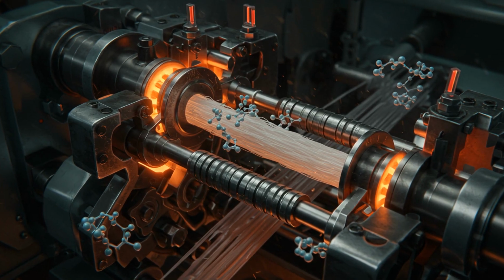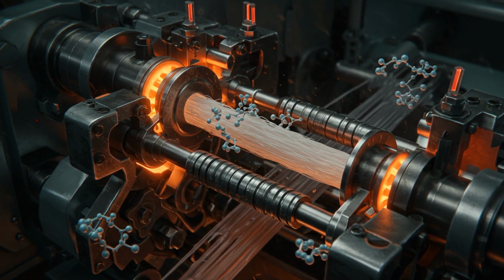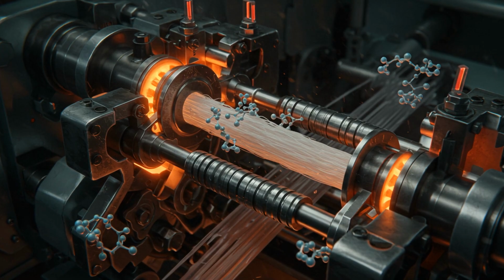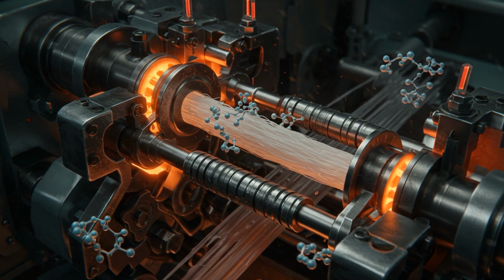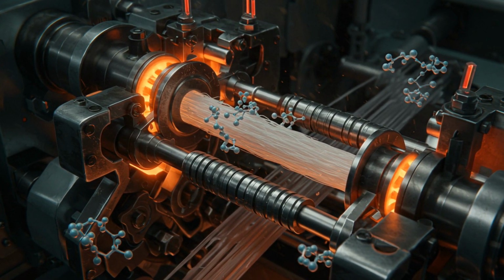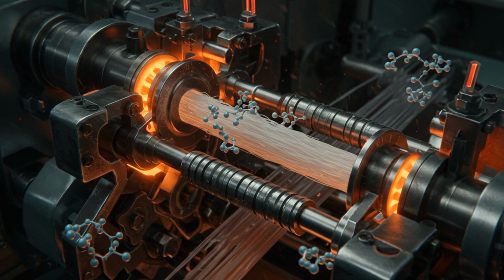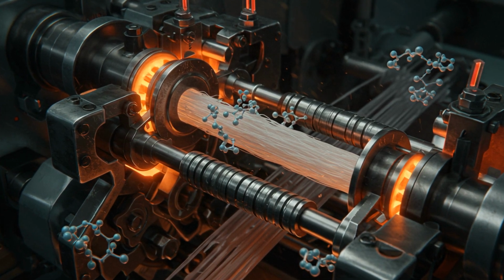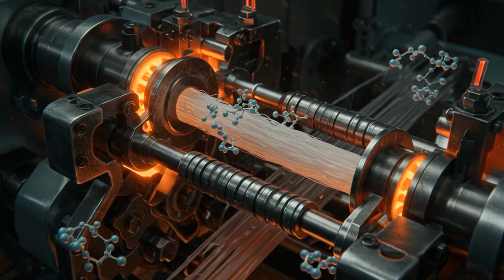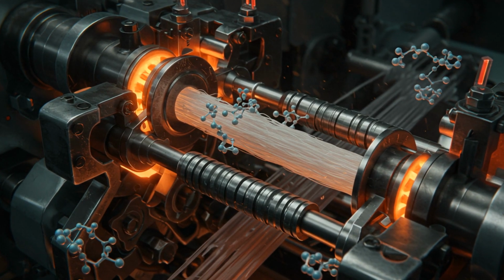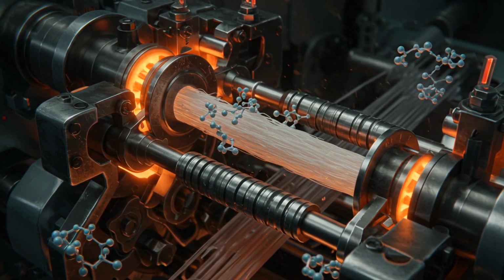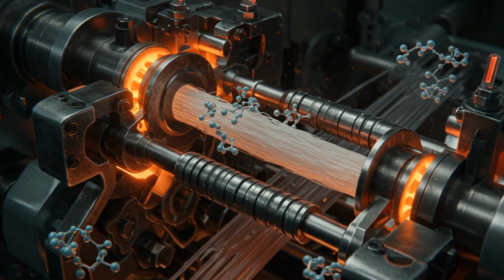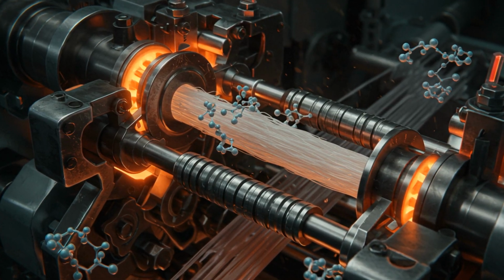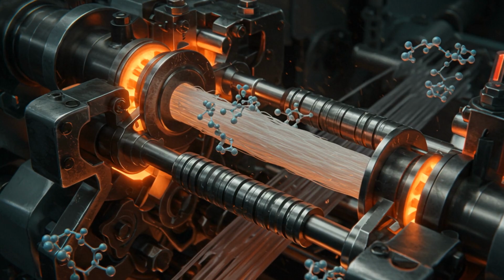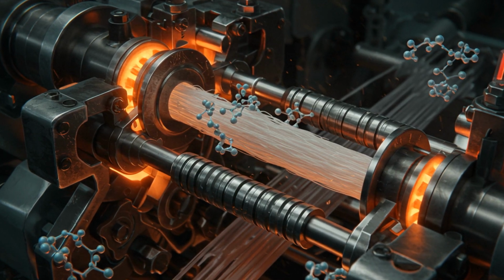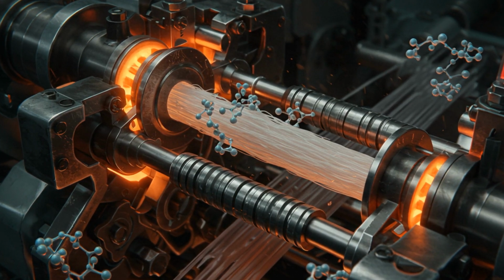Drawing stretches fibers to align polymer chains along the fiber axis, converting curly random coils into taut, load-bearing rods. This alignment is the origin of nylon strength. A freshly spun filament passes sequentially over heated godettes, metal rollers that control temperature and speed, then is pulled with draw ratios commonly of 3 to 6 times its original length. Temperatures during drawing are often between 120 and 180 degrees Celsius, hot enough to allow chains to slide and reorient, yet below the melting point.